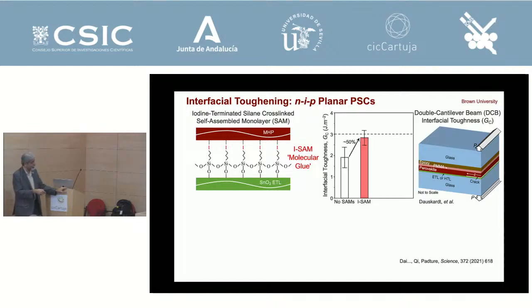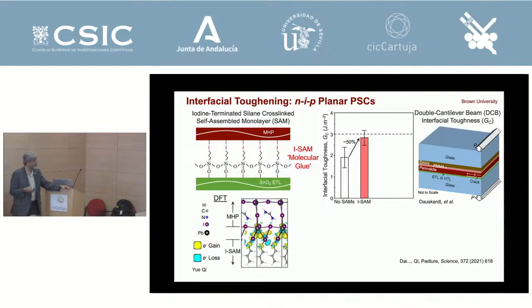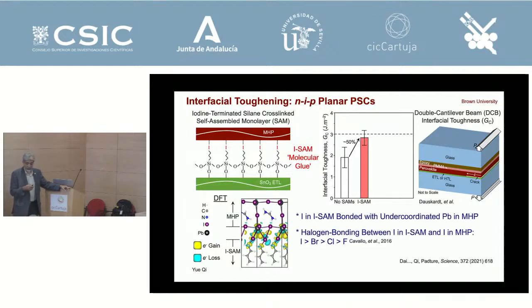And then we measure the toughness using what's called the DCB technique, double cantilever beam. You find that when you put the SAMs, the toughness goes up by about 50%. Because of this anchoring of this and the anchoring of the iodine into the metal halide perovskite. MHP is the metal halide perovskite. And so we work with a colleague who does DFT modeling. And so this is the iodine termination of the SAMs, and that's the perovskite. And what we discovered is that it actually has two kinds of bonding. One is the iodine in the SAMs bonds to the undercoordinated lead in the perovskite. And then there is a halogen-halogen bond between the iodine in the SAMs terminal group and the iodine in the perovskite.